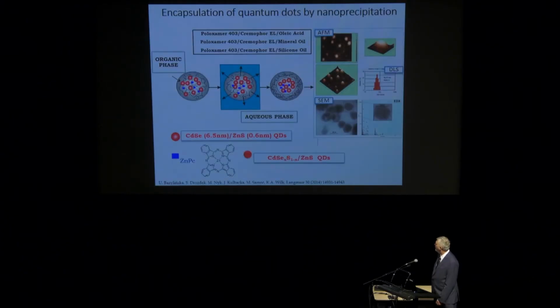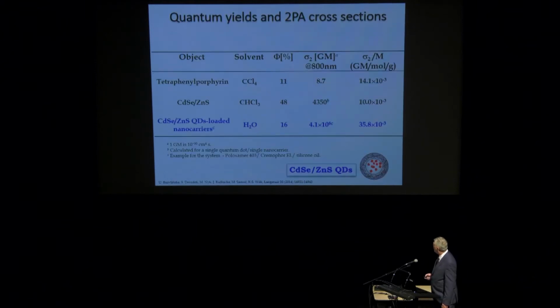So this is an example. Nanocapsules containing quantum dots, cadmium selenide, core shell quantum dots, and the photosensitizer, which is a zinc phthalocyanine in this case. We encapsulate them, and then what we find is that really such a capsule has a brightness which is 1,000 times bigger than the brightness of a single quantum dot. Could we get that using a bigger quantum dot? Of course not. Because a bigger quantum dot would not be a quantum dot. But if you have 1,000 of them inside the nanocontainer, it's a very, very bright species. Very, very easy to detect using nonlinear microscopy.